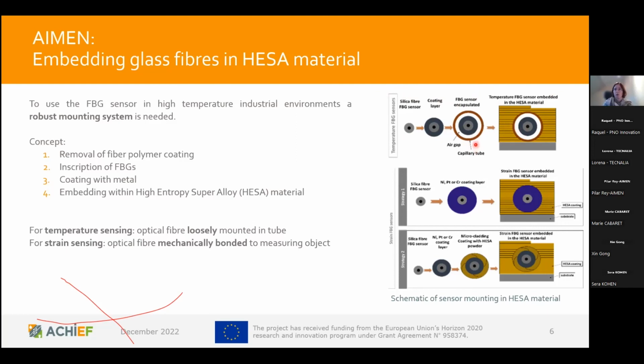So we propose to actually mount it in a capillary tube, and that then leads to a thermal equilibrium with the surrounding material. For the strain sensing, we propose to actually bond the HESA material to the metallic coating that is around the FBG sensor fiber. And we thought we could either achieve that with a thick enough metallic coating or with an intermediate microcladding coating step to make sure that the fiber is not harmed through the additive manufacturing step.